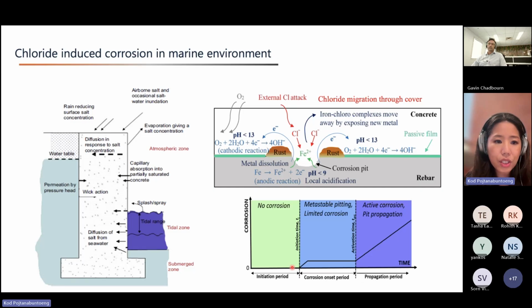And this slide basically shows a couple of mechanisms related to that. So chloride ions diffuse into the concrete, compromising the passive layer and causing the steel reinforcement to corrode. The main question is how long it will actually take, so that the asset owners can prioritize, predict and schedule the inspections before failures occur beyond repair or costly repair needs to be undertaken.